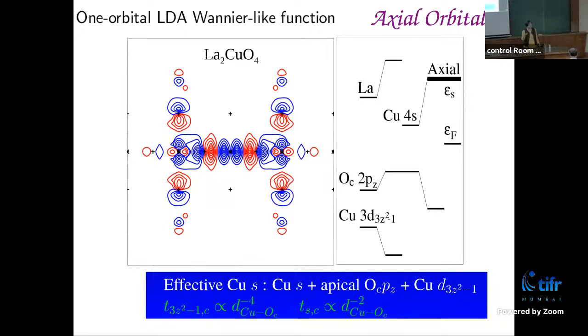But what it can couple to is copper 4s, which is empty and which is spherical in nature. So copper 4s, being spherical in nature, can couple to dx square minus y square, as well as to oxygen PZ and even further orbitals like lanthanum Ds. This is exactly what is shown here: the copper 4s, which is empty, interacts with oxygen PZ and also with the lanthanum, and maybe also with copper 3z square, because that is also ml equal to 0. So all ml equal to 0 can connect to each other. And that gives rise to an effective hybridized object, a composite object, which is an axial orbital.